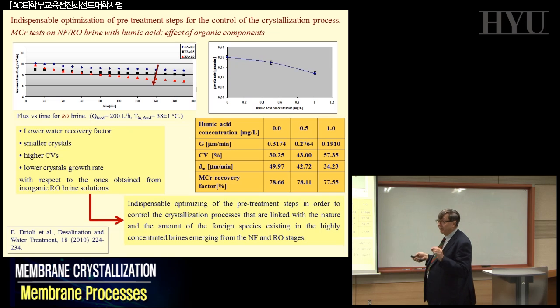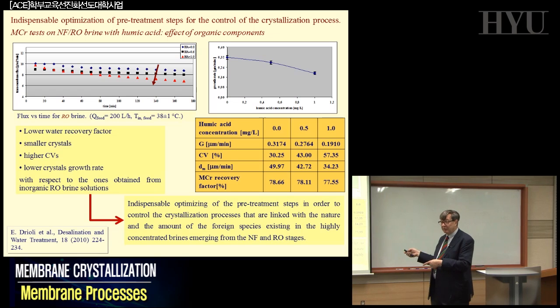What we are adding here is a very, very low concentration of humic acid. So any organics present in the system have to be removed as much as possible. That's why I was mentioning we are starting to work with membrane bioreactors to avoid this kind of effect on the transmembrane flux of the system. So you have a lower water recovery factor, you have smaller crystals, higher variance of the system, lower crystal growth rate, etc. Basically, you have to introduce a new way to pre-treat, beyond traditional nanofiltration and reverse osmosis, if at the end you want to obtain